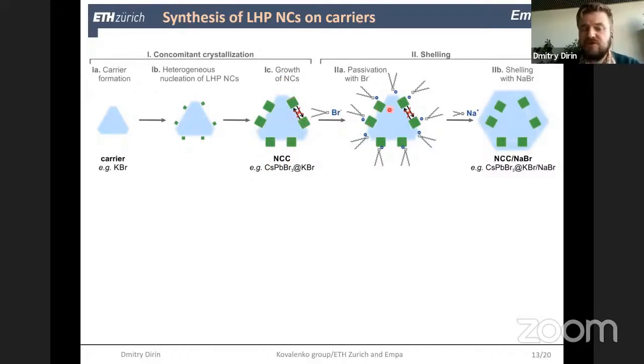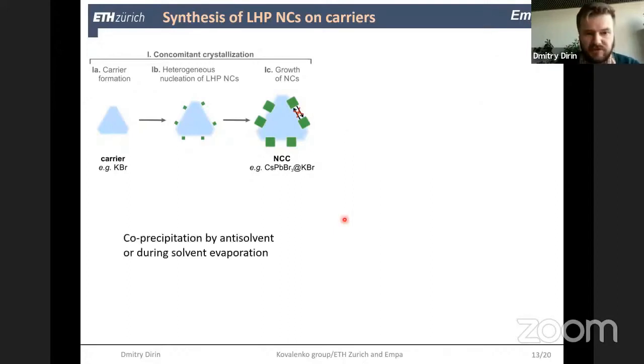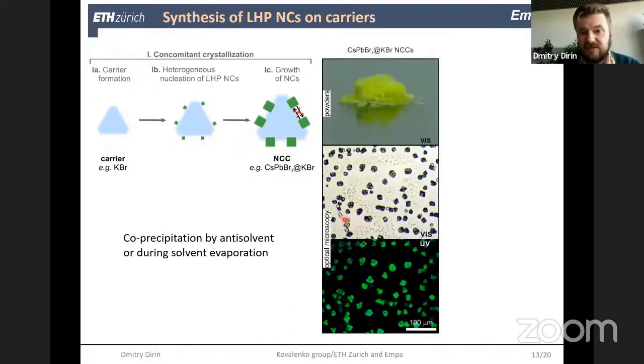because the nanoparticles are anchored and they don't merge, we can attempt a shelling with sodium dodecyl sulfate and didodecyldimethylammonium bromide, which in toluene precipitate in the form of sodium bromide and then create a shell of sodium bromide around the nanoparticles. But let's go step by step. So on the first step, we already can see a fully inorganic material. Our nanoparticles are not passivated by any ligands, but they exhibit a bright emission.